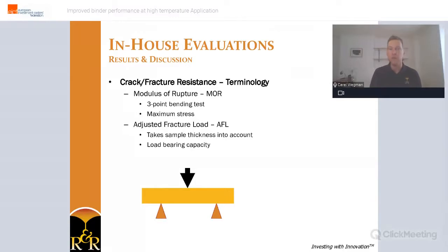MOR is an intrinsic material property of shell strength. It's measured through a three-point bending test, and it measures the maximum stress a sample can handle. AFL is performed by the same test, but it takes the sample thickness into account and is therefore a measure of the load-bearing capacity. Thus, a shell material with a low MOR can achieve the same degree of crack resistance when it has more shell thickness.